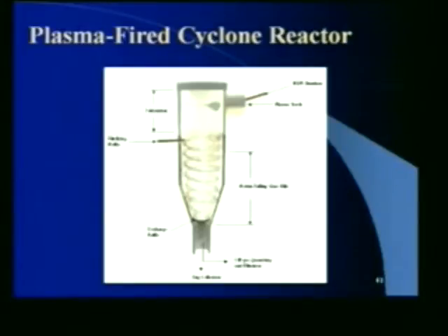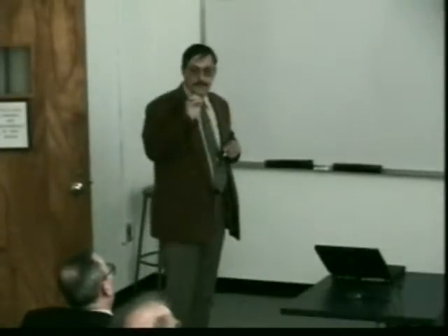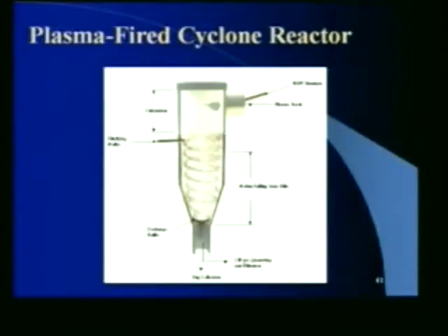You might imagine, again schematically, what's going on: we have a calcination zone, and then we have a vitrification zone. Up here in the top part where we have the plasma torch, we have a very high temperature flame, and we're injecting the material into that flame zone. Because of the closed top, you actually form a recirculation zone where you get very, very good mixing right where that plasma torch comes in. So everything sees very, very high temperatures, fairly strongly oxidizing conditions. But a little lower down where you inject the vitrifying media, because of the cyclonic flow, you start forming forces that throw the dust or solid particles to the wall. So you have this glass frit which captures that and then goes down.